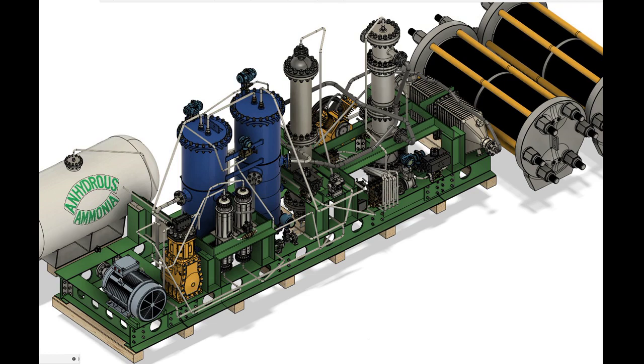Diaphragm life as a consequence is severely reduced, above and beyond the already relatively poor life caused by thermal and fatigue stresses. This is even so in a continuous operational regime, such as with coal gasification, because filtration of micron-scale particles is very challenging. It requires no more evidence to conclude that this compression technology is simply not satisfactory for our requirements and will produce headaches for operators.